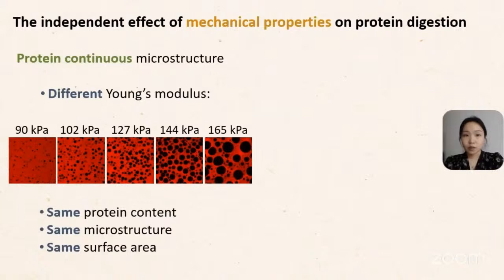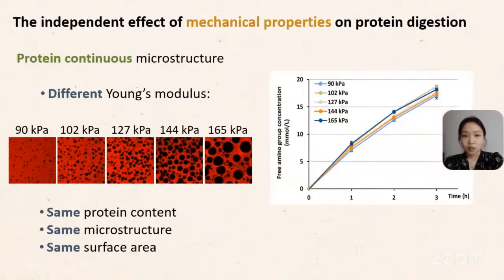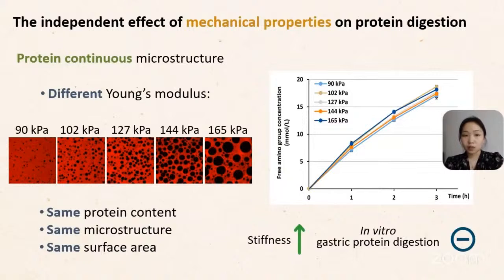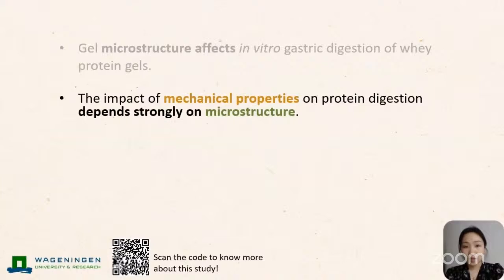Then we also tried with protein-continuous gels. So we had these gels with a series of Young's modulus, and they all showed protein-continuous microstructure. However, there were no significant differences in free amino group concentration during static digestion, which suggests that for the gels with protein-continuous structure, increasing the Young's modulus or the stiffness did not affect the in vitro gastric protein digestion. This result shows that the impact of mechanical properties on protein digestion depends strongly on microstructure.